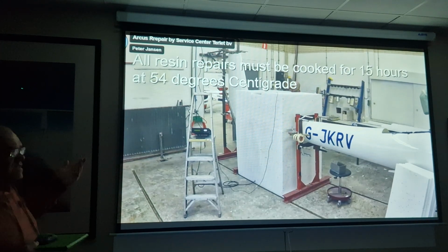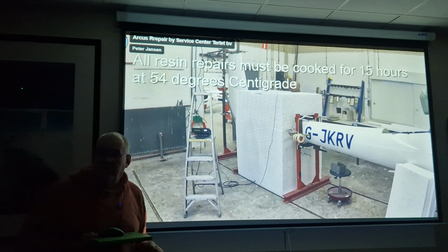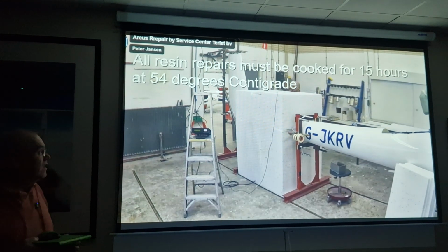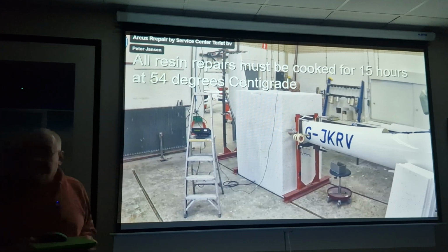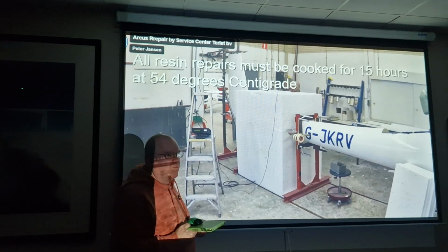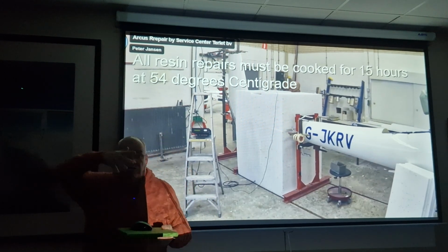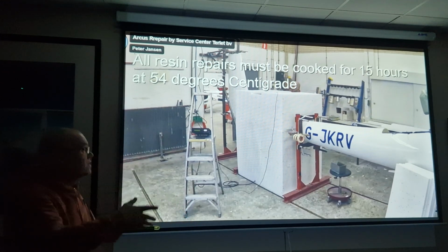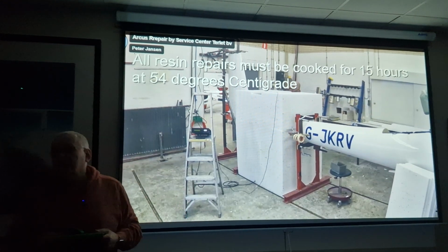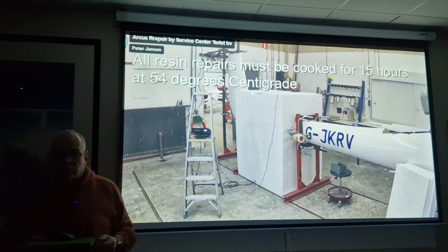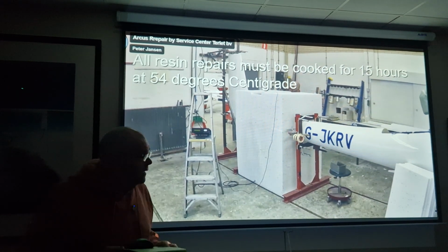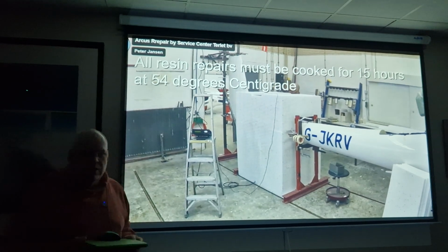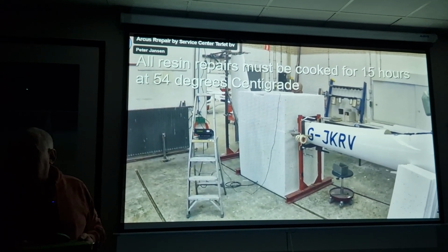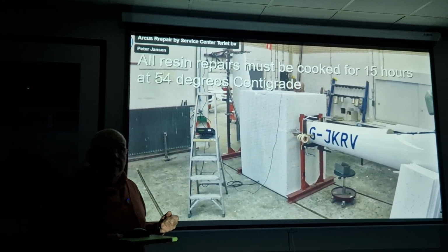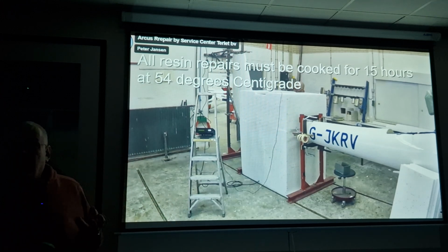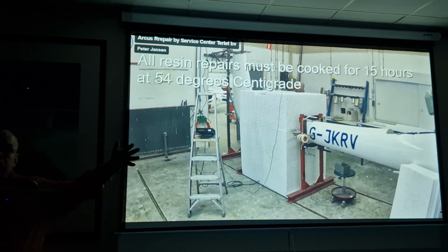So what's the difference between this and, say, a Formula One car or an airliner or fighter jet made with modern carbon material? The actual methodology is identical. The difference is they use what's called pre-preg materials. They buy materials that are literally pre-impregnated, put them into their molds, and cook them at 160 degrees. Much higher. I mean, we're talking burning pizza temperatures for quite a few hours. That means all the molds and jigs have to go to 160 degrees, and in terms of tooling, that's quite a big ask, because whatever you're building has to expand and contract with the jig or the mold.